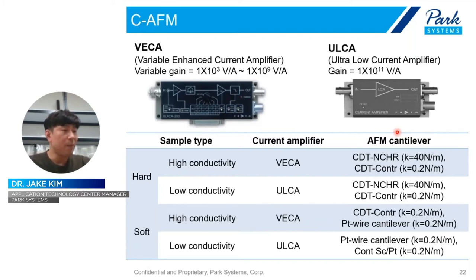The key part of conductive AFM is this current amplifier. There are two types. One is VECA, the variable enhanced current amplifier, and the other one is ULCA, the ultra low current amplifier. The difference is the detecting range. Roughly speaking, if your sample has a high conductivity, you should apply the VECA. But if your sample has a low conductivity, for example, less than a few picoampere or less than picoampere, you have to apply the ULCA, the ultra low current amplifier. So depending on the signal or the sample type, we can apply each current amplifier.